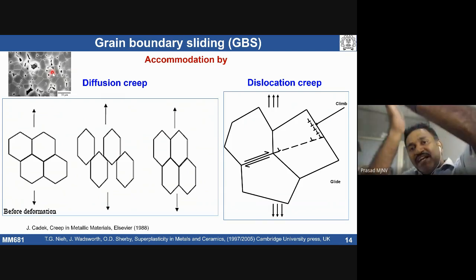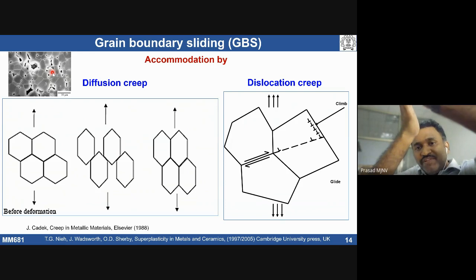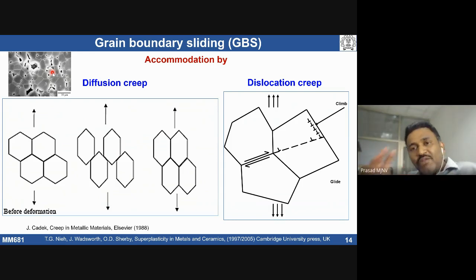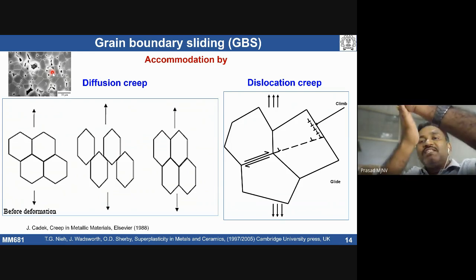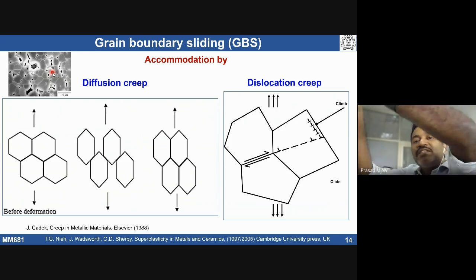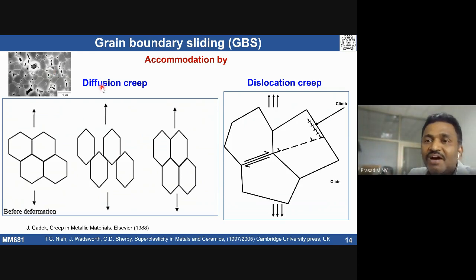Because of grain boundary sliding, a discontinuity is going to happen in polycrystalline materials. It has to be accommodated. If it doesn't accommodate, it's going to lead to failure. Even a 1 micrometer grain size has a large grain boundary area. The problem here is that at low temperature, diffusion is low. Whatever cavities or discontinuity have been developed by grain boundary sliding are not being accommodated at low temperature. At high temperature, it can be accommodated by diffusion or dislocation, because some kind of climbing can take place. At high temperature, you can see climbing activities, because the higher the temperature, the easier climb or cross slip can be. Those are high temperature phenomena.